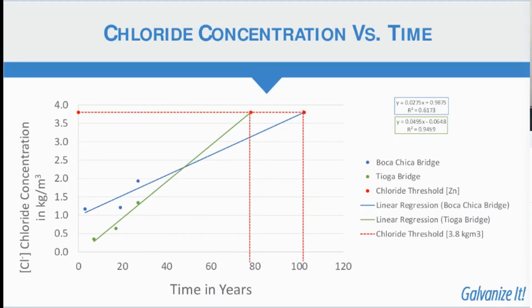To explain, I just want to show you a diagram using real-world data of two bridge decks reinforced with galvanized rebar in different types of high chloride environments. One is the Boca Chica Bridge exposed to a coastal marine environment in Florida, and the other is the Tioga Bridge in Pennsylvania, which is exposed to regular use of de-icing salts in the winter. With historical data, the chloride concentrations were plotted, and then these bridges were not expected to reach that chloride threshold for the onset of zinc corrosion until 78 to 104 years into their life.